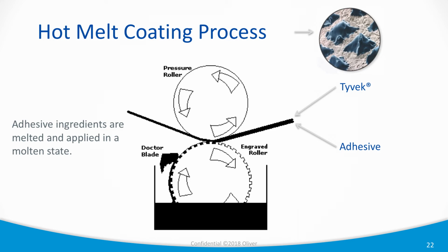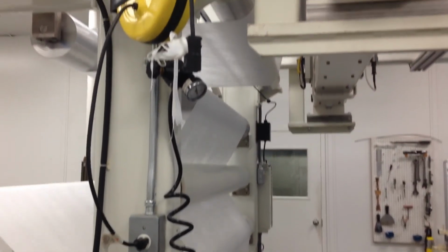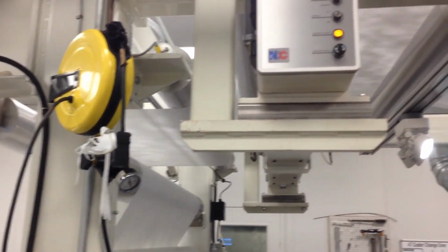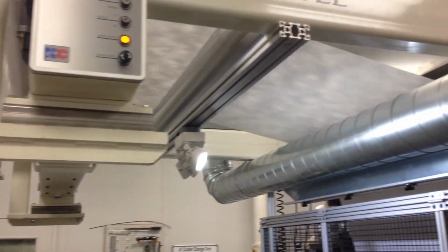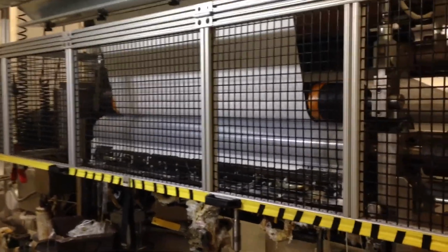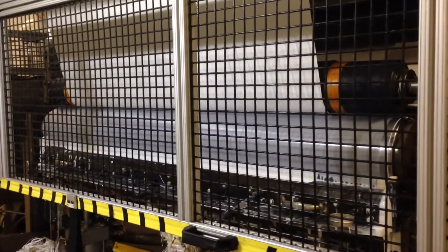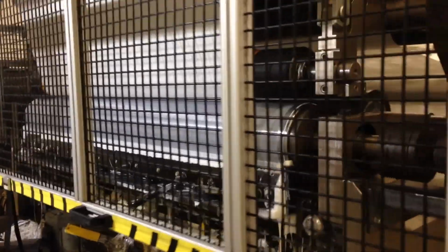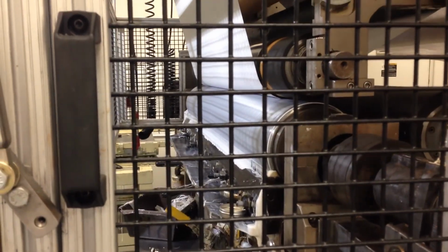We'll show you a quick rundown of the actual coating process. You can see master rolls. We're printing the adhesive or coating the adhesive roughly 55 inches wide. It goes through a series of rollers. And then you'll see a silver colored cylinder here. That's that etched cylinder that I was just talking about. So it's picking up micro dots of adhesive. It's got etched micro pockets picking up the adhesive out of the fountain. The doctor blade is scraping off the excess adhesive. And then in between the interface of that impression roll and that silver cylinder is where we're laying down that adhesive coating.